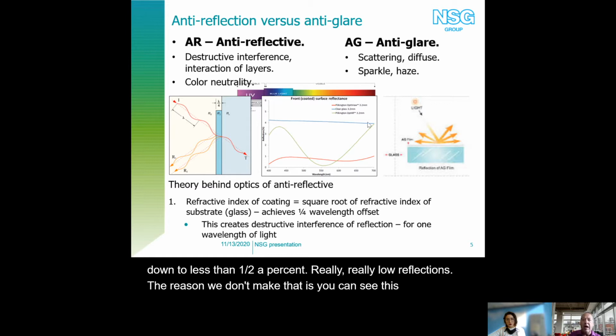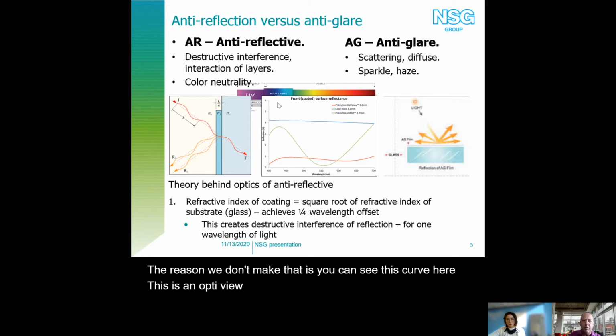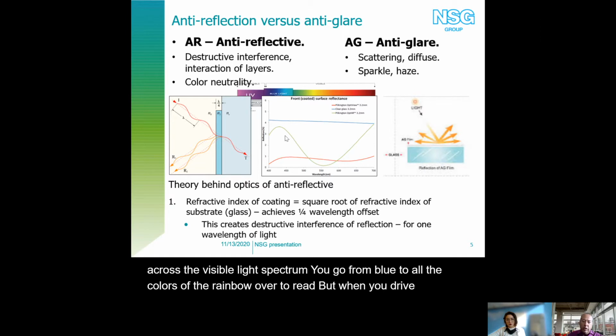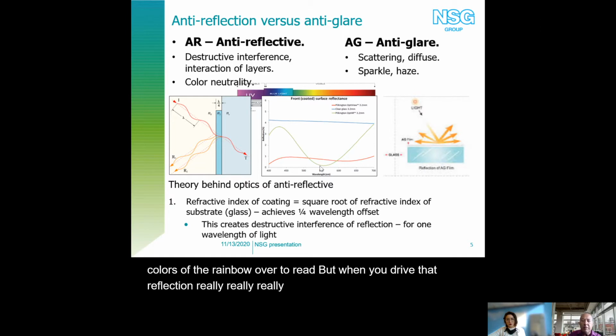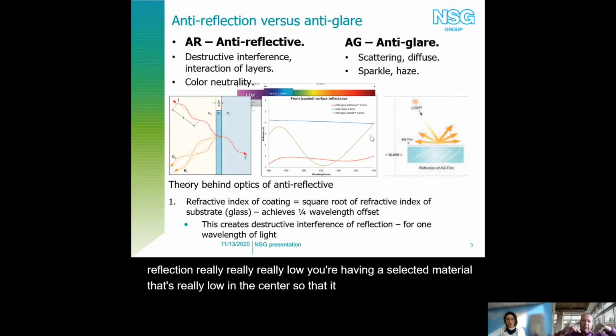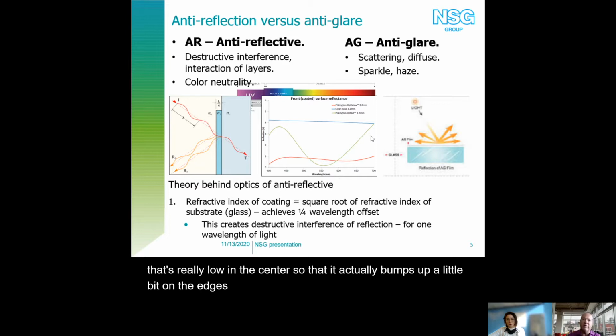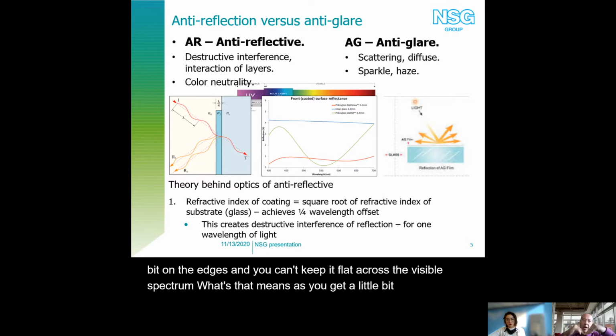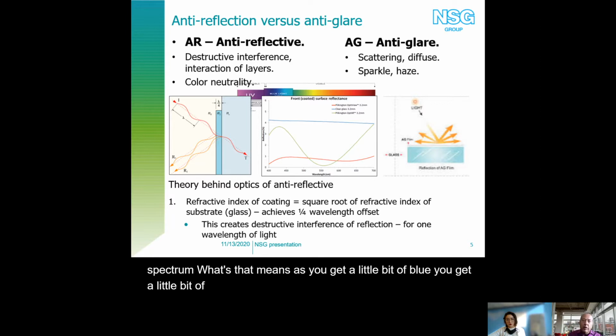The reason we don't make that is you can see this curve here. This is the OptiView, across the visible light spectrum, going from blue through all the colors of the rainbow over to red. But when you drive that reflection really, really low, you're having to select a material that's really low in the center. So it actually bumps up a little bit on the edges, and you can't keep it flat across the visible spectrum. What that means is you get a little bit of blue, you get a little bit of red, and the color of the coating actually looks purple, especially when you get it off angle.